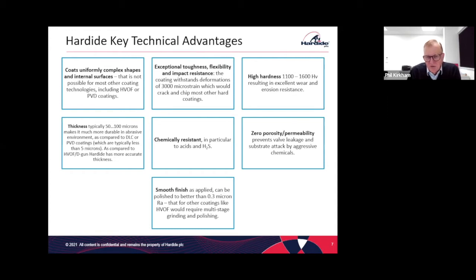The hardness of the coating can be varied, and we can produce anything from pure tungsten, which has a hardness of around 300 Vickers. Vickers is the method used for measuring hardness of these type of coatings, up to 3,200, which is effectively pure tungsten carbide. So anything in between, we've found by practical experience over the years that somewhere in the middle of that, between 1,100 and 1,600 Vickers hardness, is the best optimum place to be for wear resistance and erosion resistance.